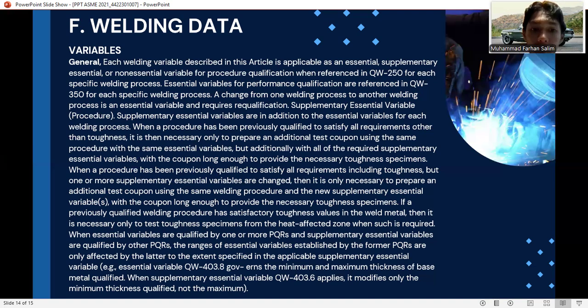When a procedure has been previously qualified to satisfy all requirements including toughness, but one or more supplementary essential variables are changed, then it is only necessary to prepare additional test coupons using the same welding procedure and the new supplementary essential variables, with coupons long enough to provide the necessary toughness specimens. If a previously qualified welding procedure has satisfactory toughness values in the weld metal, then it is necessary only to test toughness specimens from the heat affected zone when such is required.